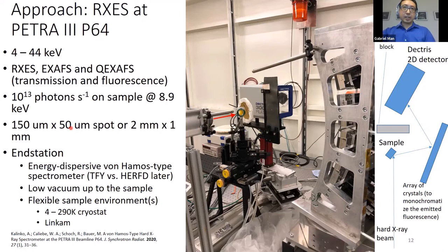So at my beam time, we used the energy dispersive von Hamos type spectrometer. So you can see the side of it where you can see an array, a column of four crystals. There's a few other columns over here. And so what the crystals do is that they sort of focus the emitted fluorescence in the vertical direction and disperse in the horizontal direction onto a two-dimensional detector.